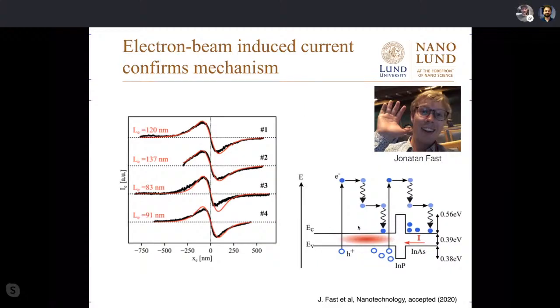Even with a very simple model, assuming some kind of exponential decay of the hot carriers, you can fit this and extract some value of effective relaxation length, which turns out to land around 100 nanometers, with this experiment, which uses huge energy to create electron hole pairs. So the value itself is not that important. It just means that we can confirm that the process works the way we had imagined.